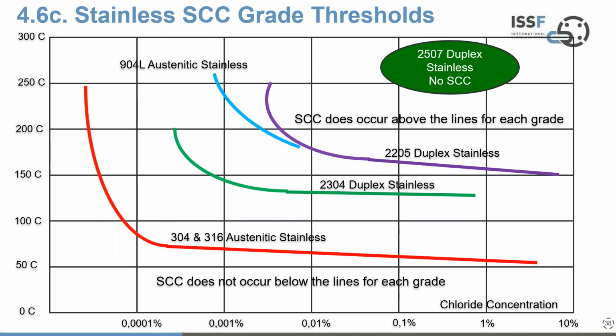And if you take any one of the lines, so the red line, which represents 304 and 316 austenitic stainless, if your operating temperature is low, below 50 degrees centigrade, you're not going to suffer stress corrosion cracking. But once you start to go above that threshold, then increasingly high chloride concentrations will move you into a dangerous ground. So if you had an operating temperature of 100 degrees centigrade and the chloride concentration of 0.1%, a 304 or 316 austenitic stainless would be at risk of stress corrosion cracking. You have to move up that chart to select an appropriate duplex stainless steel in this case.